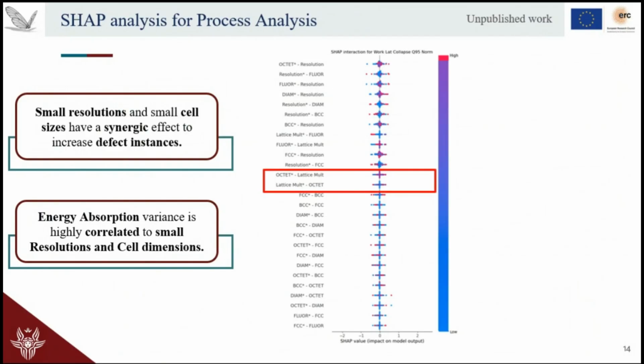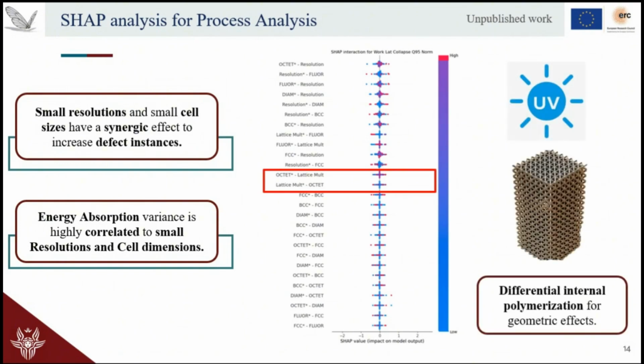As you can see here, we have a positive interaction between those two parameters. What does that mean? The octet structure is very dense, very packed, and this interaction appears only for a small cell scale. So that means that due to the geometrical effects, there is not a homogeneous polymerization in the lattice structure, and that's causing the appearance of defects inside of the part.